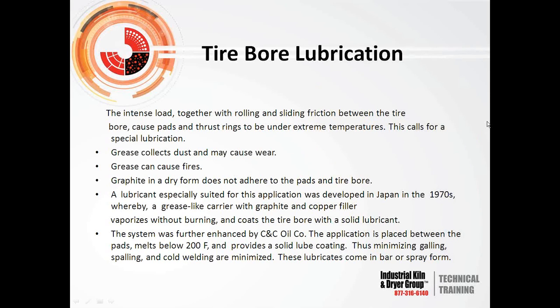Okay, since this is such a problem in the industry, with the wear and the wear rate on all these tire mounting systems, in your opinion, what should we do for lubrication? Well, definitely what you want to do is lubricate the bore of the tire with a bar that will melt due to the shell temperature, and that'll lubricate the pads, and that'll really slow down the rate of wear on your tire pads and reduce the development of a high gap, high creep. So there are what we call lube blocks that you stick in between the tire and the shell, which will take care of that problem. So we absolutely recommend this.